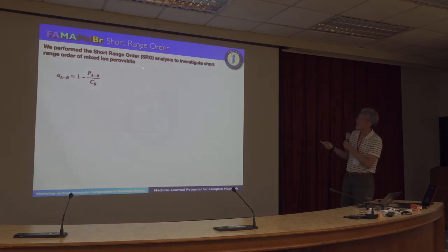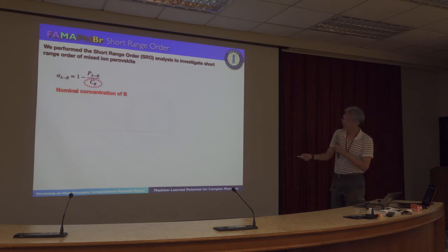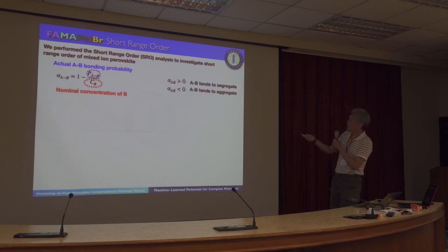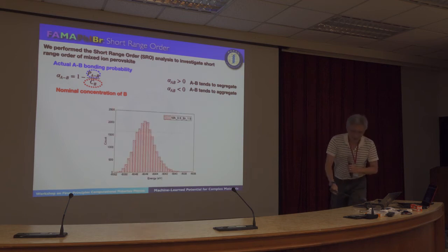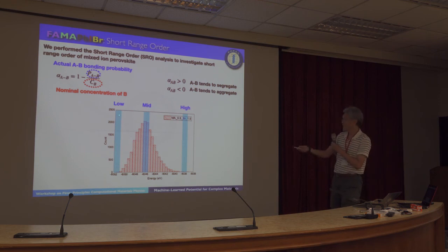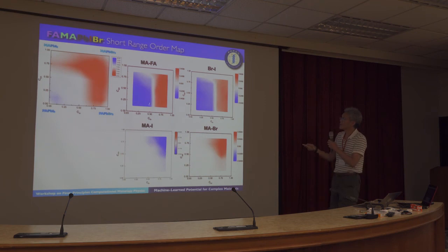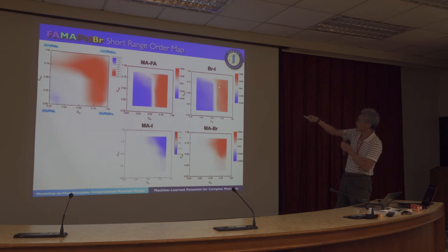So we also want to sample the short range order. So we use this short range order parameter. Here we have a nominal concentration of B, and here is the actual AB bonding probability from our simulations. So we know that if this is bigger than 0, that means that AB atomic pairs tend to segregate. And then we basically take 3 different categories: low energy, mid energy, and high energy regimes, and sample this short range order parameter. Oh, I'm sorry. Here we only show the short range order of the lowest energy structures. So here you can see that for MA and FA pairs, we got phase segregation. We also got segregation of bromine and iodine pairs here.